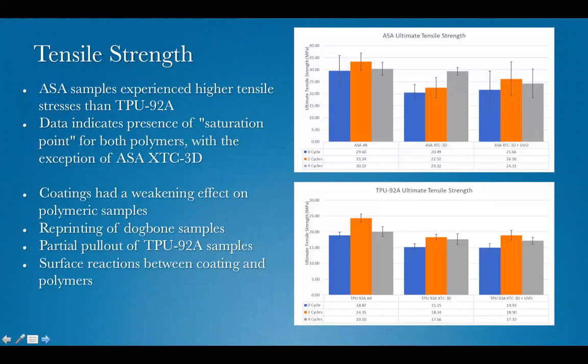ASA tensile samples exhibited a greater maximum tensile strength over TPU-92A samples. Although both uncoated sample sets did not exceed a 10% decrease in strength over 4 cycles of immersion, it should be noted that TPU-92A experienced high strains relative to ASA counterparts. Tensile samples overall contradicted the group's hypothesis, which was that uncoated samples would consistently degrade in strength at some rate with respect to time, and the addition of coatings would mitigate this effect.